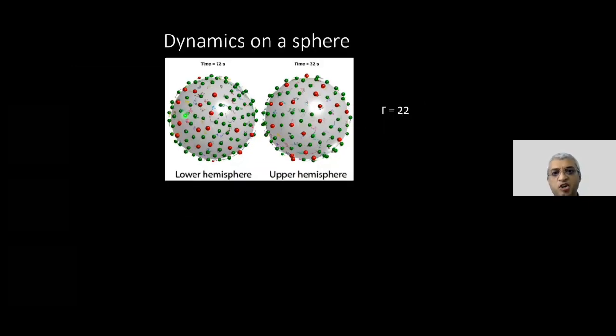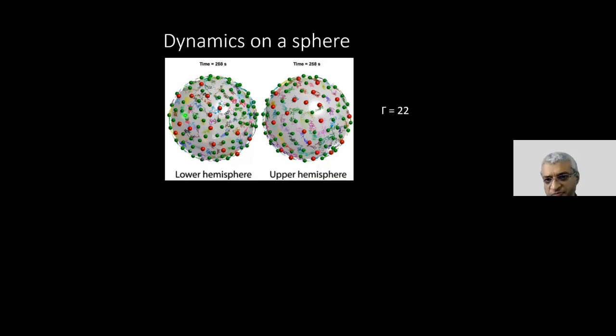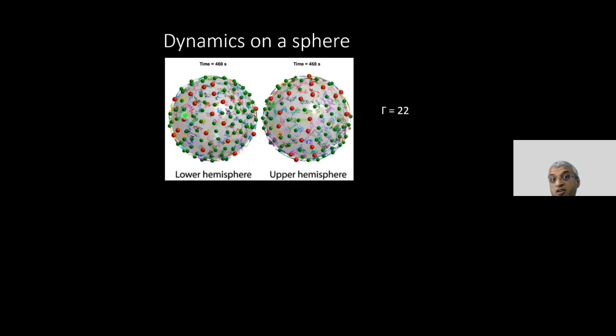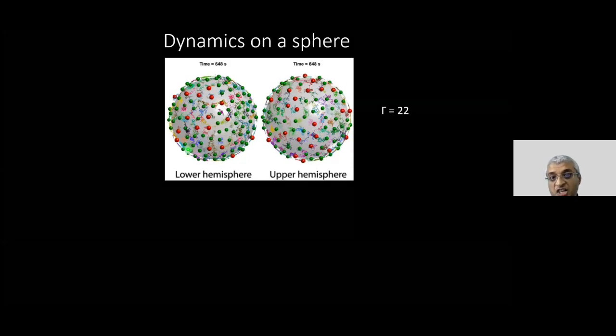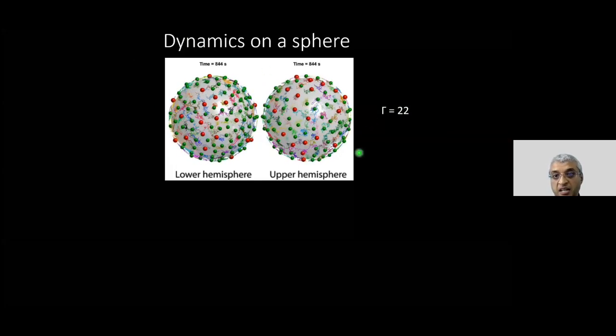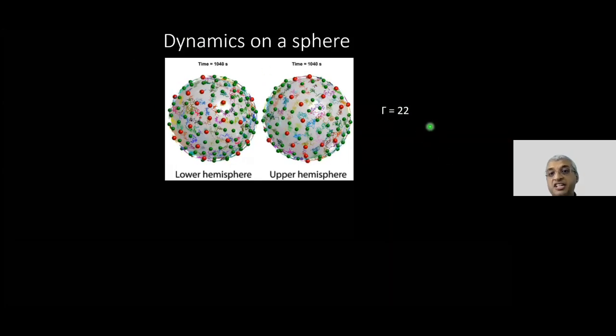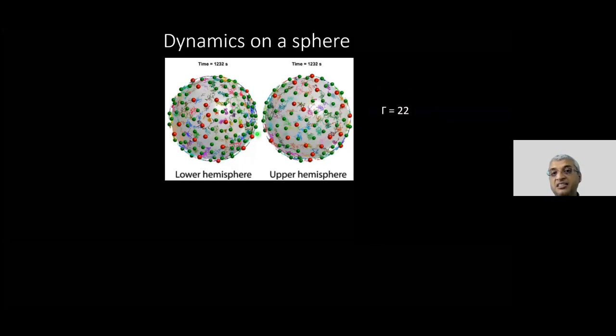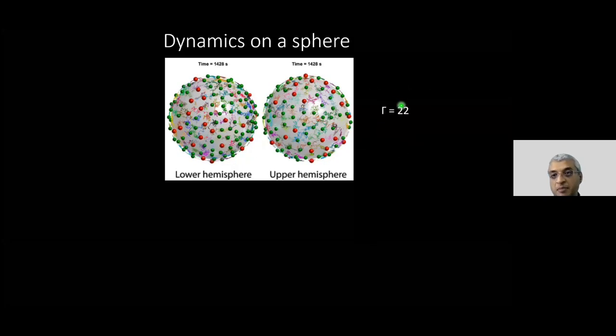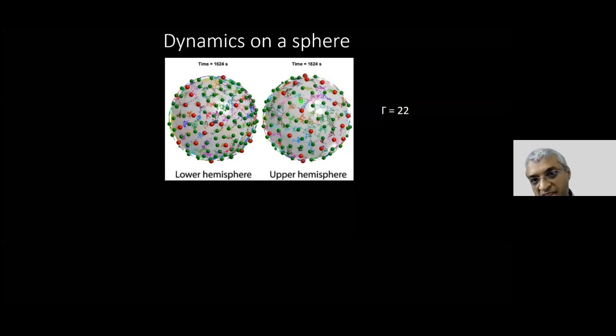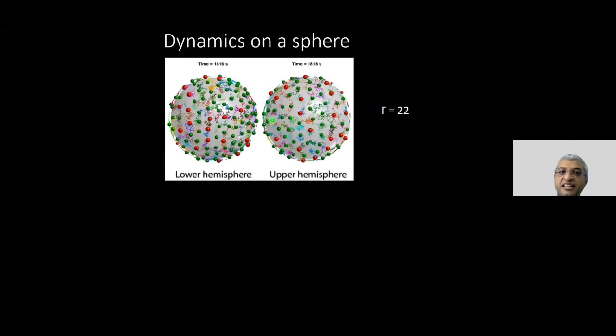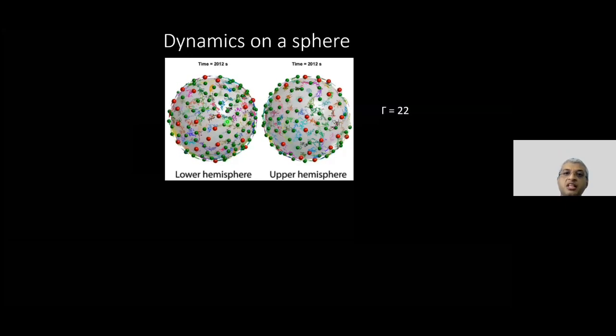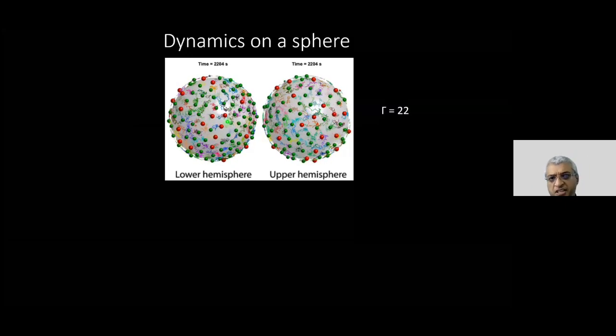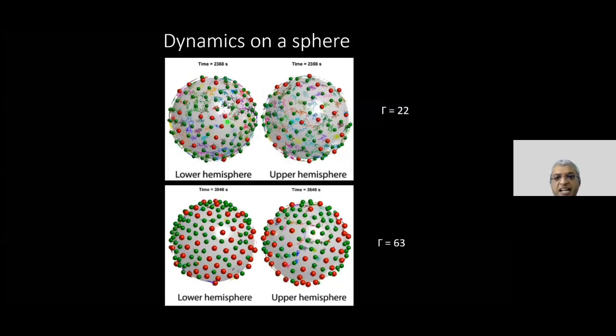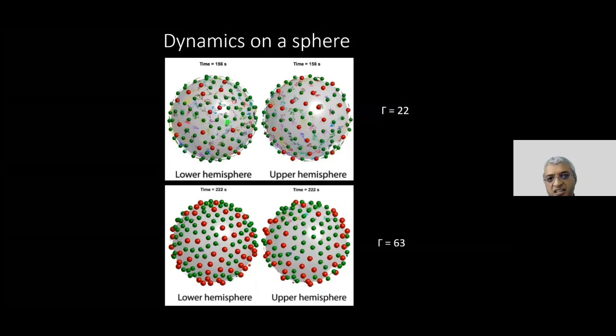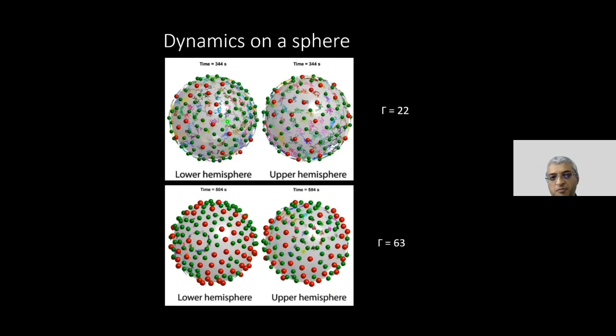So I basically have a droplet on which I have particles freely diffusing around, but on a curved surface. To avoid crystallization, I have taken two different sizes of these particles, and these are the dynamics that you see. Just like phi, my parameter that controls glassy dynamics is called gamma, which takes into account both the number density of the particles and the fact that these are charged particles, which means the interactions are dipolar at the interface. This is at a higher gamma, where the system is more frozen.